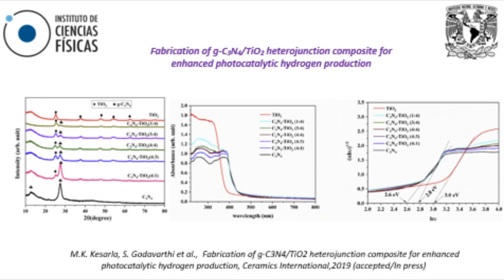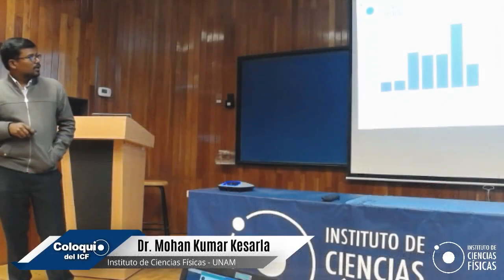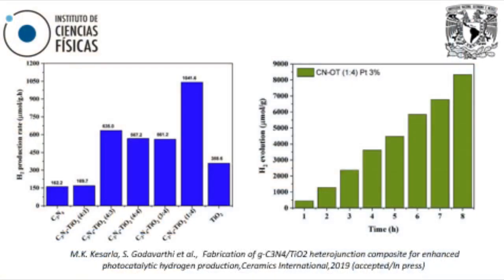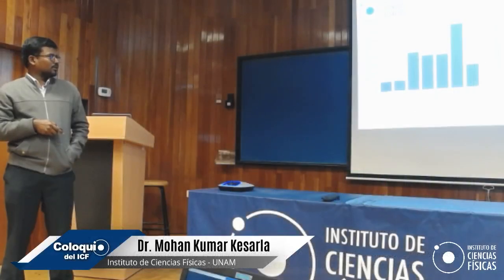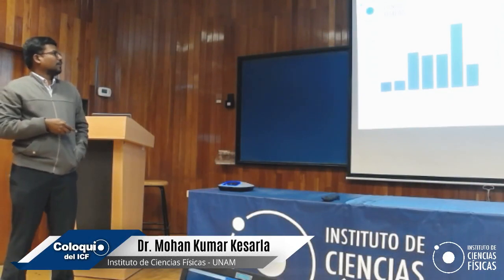If you look at the various compositions, we got C3N4 to titanium oxide 1:4. Look at the hydrogen production value, that is 1041 micromoles per gram, which is like 200 times higher than what Markus Antonietti did 10 years before. After 8 hours of experiment, we got 8,000 micromoles per gram with the same catalyst. This was accepted recently in Ceramics International, so it is in press actually.